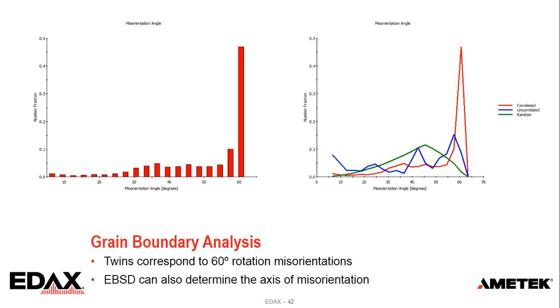We can measure this in more detail with what we call grain boundary analysis. The distribution on the left here shows the misorientation angle distribution. So this is just showing the angle between orientations. You'll see there's a strong peak there at 60 degrees. That corresponds to our twins in the material, and we'll characterize that a little bit further because in addition to angle, we can also determine the axis of rotation. The primary twin boundaries are 60 degrees about a 111 axis.